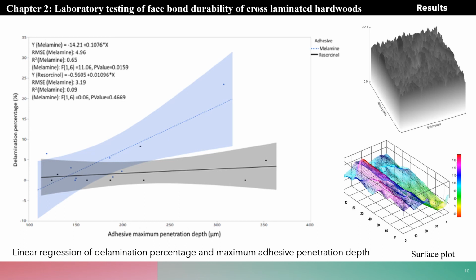And when we tried to see from the linear regression if there was any relationship between the adhesive maximum penetration and the delamination percentage, we realized that for the melamine, there was a relatively strong association between the delamination percentage and adhesive maximum penetration, although we did not get the same for resorcinol.